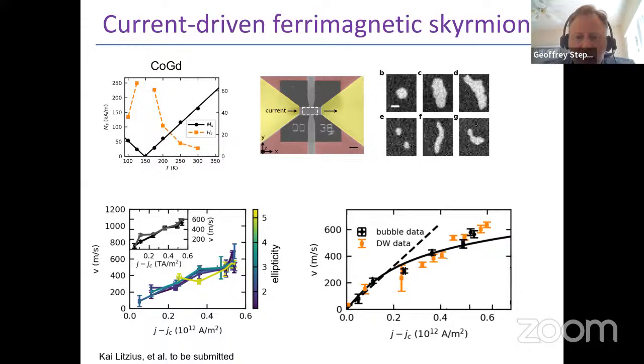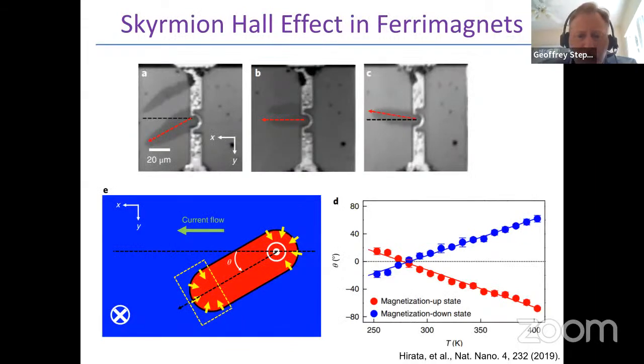So using ferrimagnetic materials at or near compensation can allow experimentally to have very small skyrmions, to have stable skyrmions at room temperature, and to have exceedingly high velocities, with all of these attributes being significantly better than one can achieve using ferromagnets. They also allow for controlling the skyrmion Hall effect.